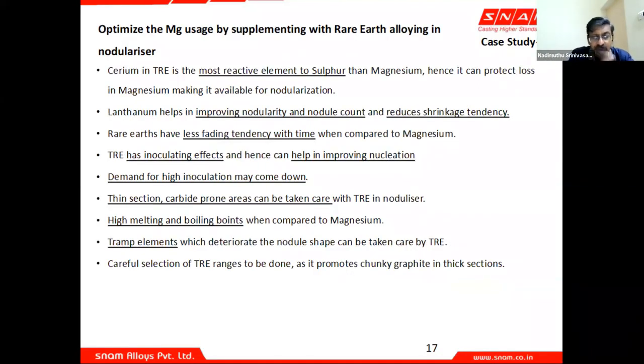So what can we do? How can we optimize the magnesium usage? We can reduce the magnesium and optimize it by adding rare earths, because, as you will see, there are cerium-based inoculants and lanthanum-based inoculants. Cerium especially is a very reactive element to sulfur than magnesium.